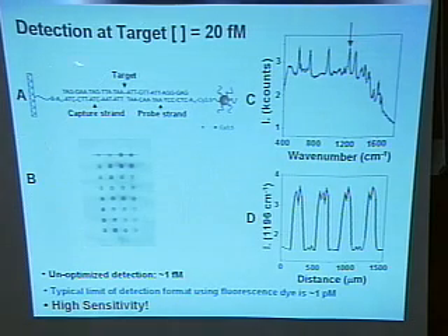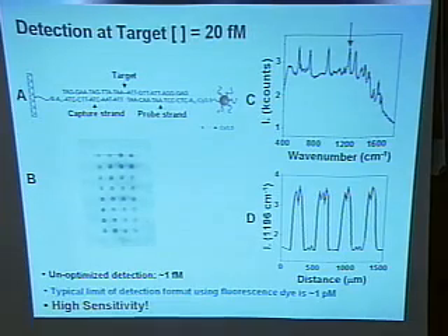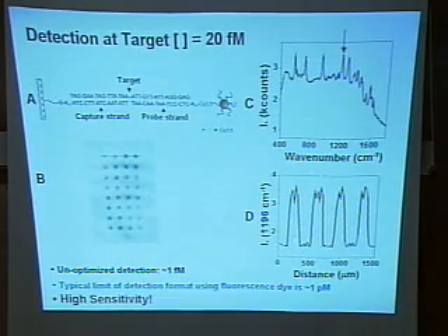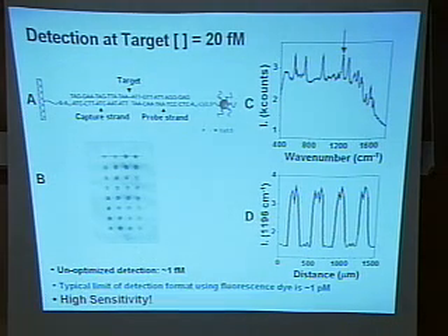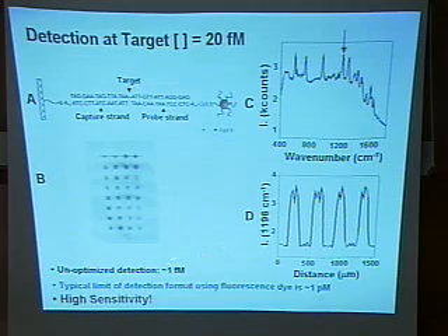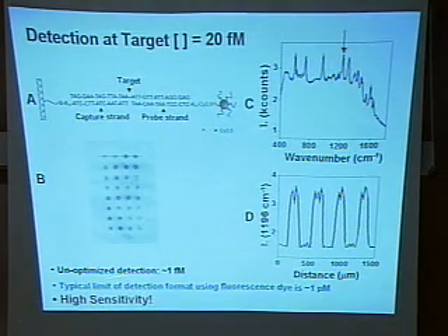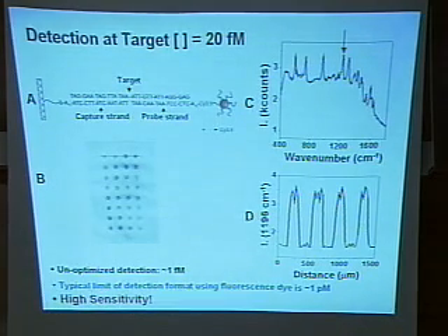This is a typical detection carried out at 20 femtomolar. Femtomolar means 10 to the negative 15 molar, really low. And we still can get a very good signal to noise ratio. And one unoptimized detection can do this at 1 femtomolar. If you do a fair comparison, using similar techniques, if you change this particle to fluorescent dyes, we can only do 1 picomolar. So it's 1,000 times better than the typical technology. We have really high sensitivity. Next, I will show you how we can get higher multiplexing.